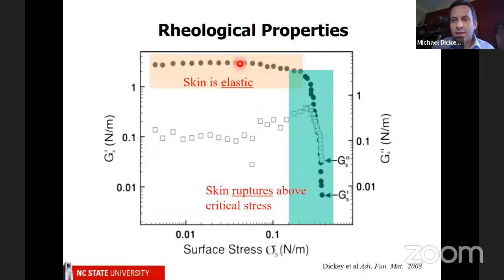And what this shows is that that oxide skin is elastic until you reach a critical stress. So right around here, you see that it drops. And what happens there is the oxide actually breaks. So this is a very important point. If you are above this stress, the oxide will break and the metal will flow. If you're below this stress, it will not. And ketchup is sort of the same way. If you take ketchup and you hold it upside down and squeeze it, nothing happens, and then suddenly it squirts out. Well, this is very similar, but a different physical mechanism, with similar behavior.